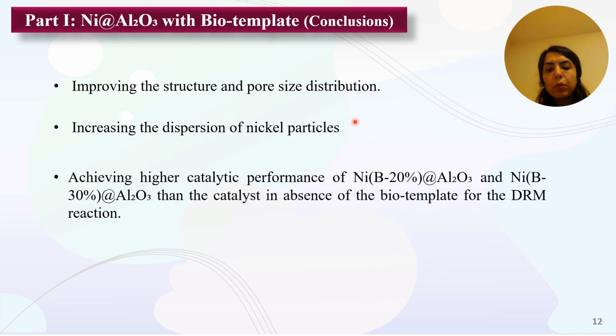So we concluded that adding biotemplate could improve the structure and pore size distribution of nickel, increasing the dispersion of nickel particles and achieving higher catalytic performance than the sample without biotemplate for the dry reforming reaction.